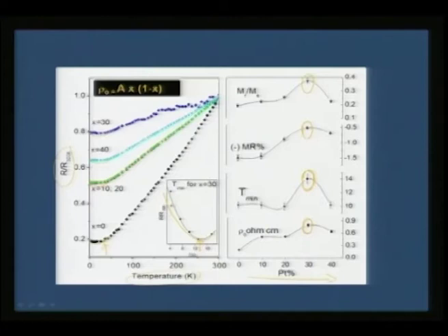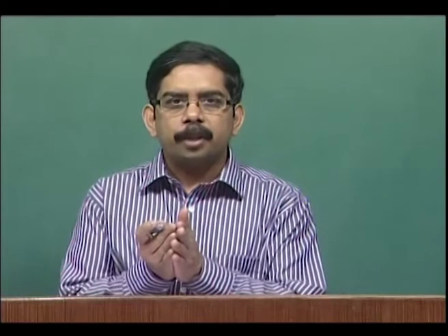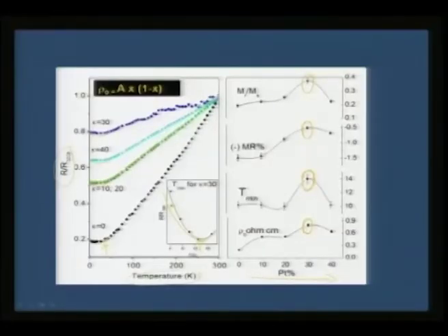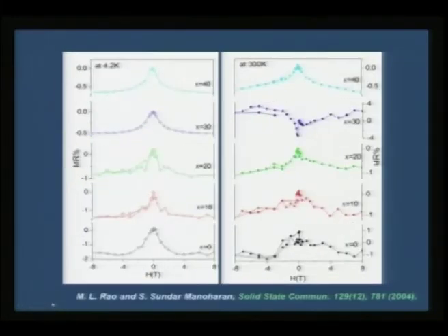So what do we see from here? We can make correlations between magnetoresistance and the local disorder in these cobalt platinum nanoalloys, and we can make several interesting observations as a function of platinum doping. So one can systematically study what is really the governing factor that controls the properties.